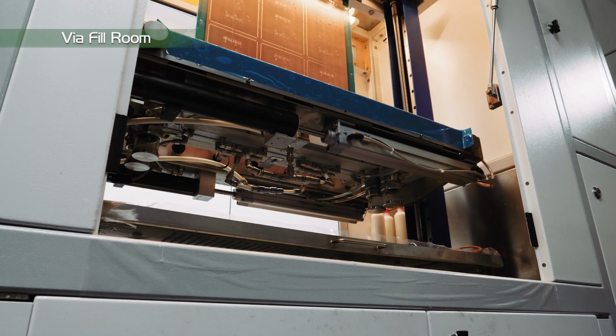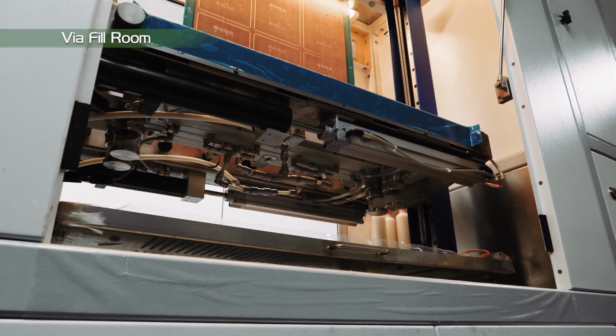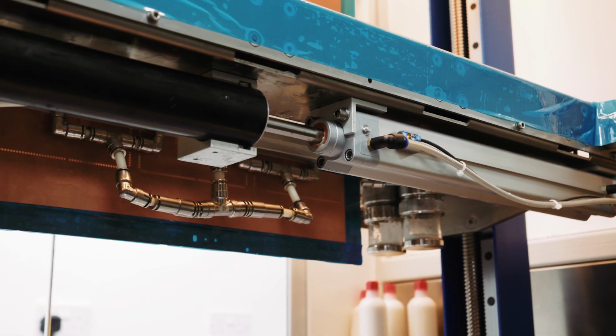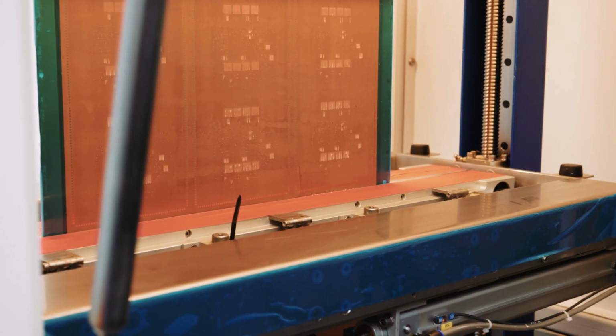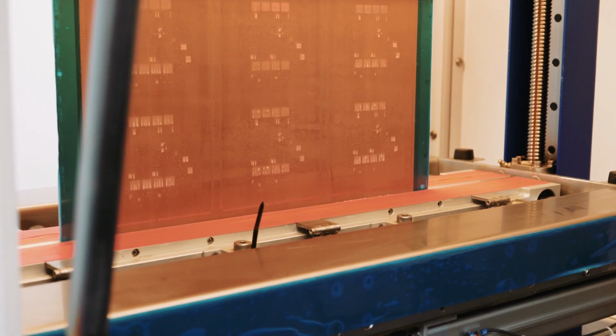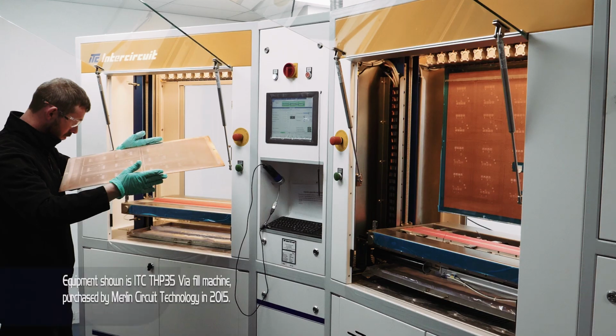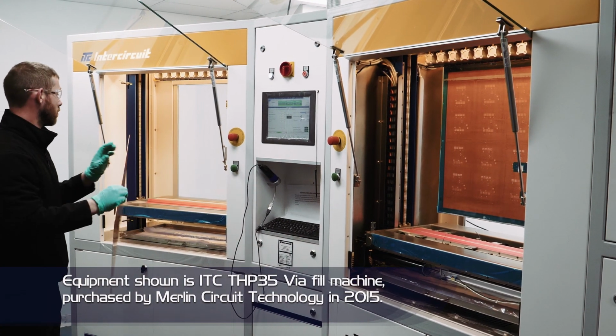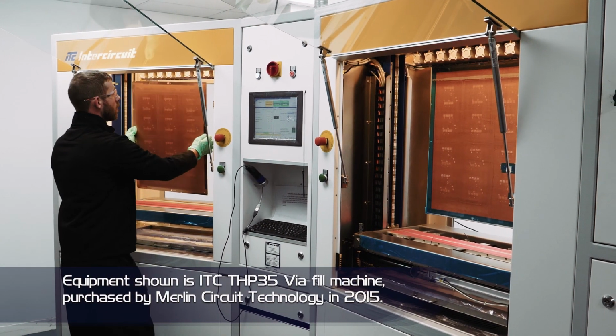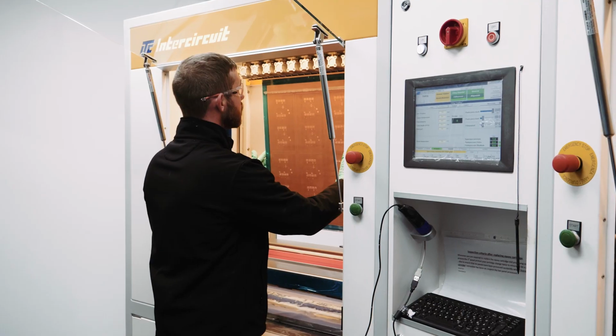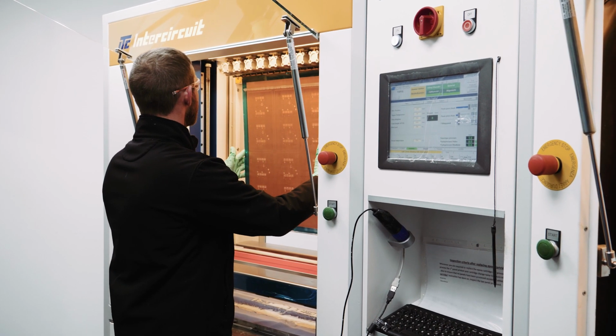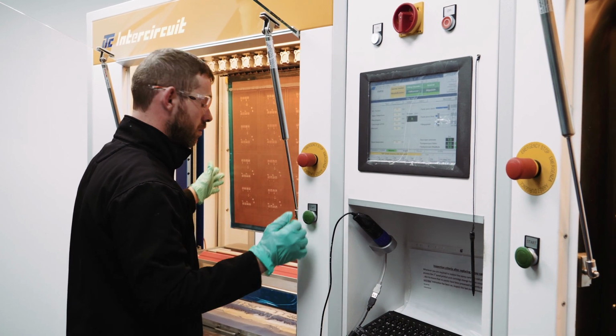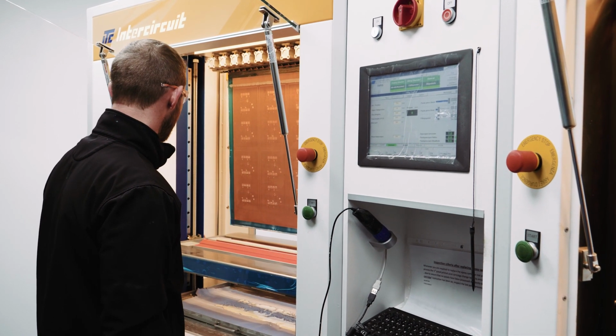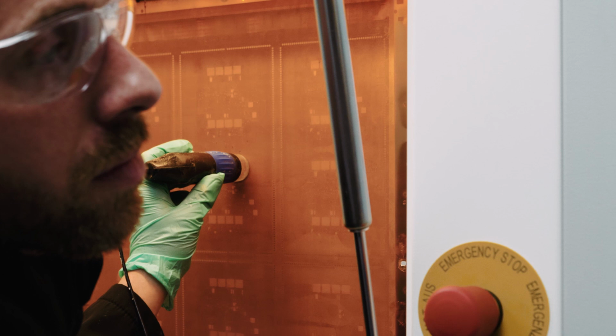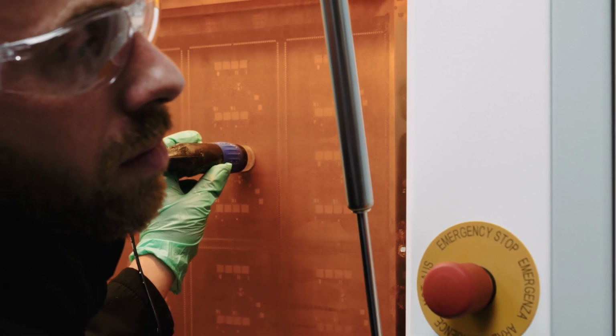The customer may request that some or all of the via holes are to be plugged with resin and capped over with copper, IPC 4761 Type 7. The ITC via fill machine has a set of vacuum heads which create a localized vacuum. The epoxy resin is then pulled into the vias due to a pressure difference. This ensures that through and blind vias can be filled 100% with no voiding.